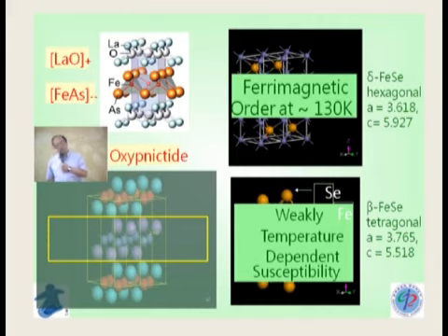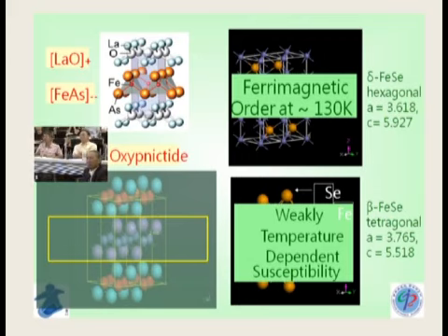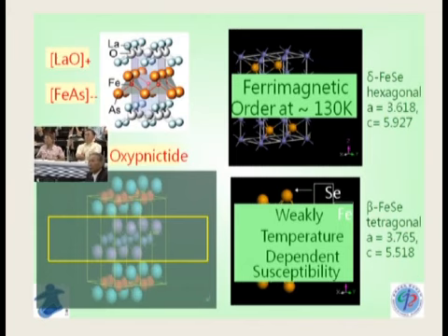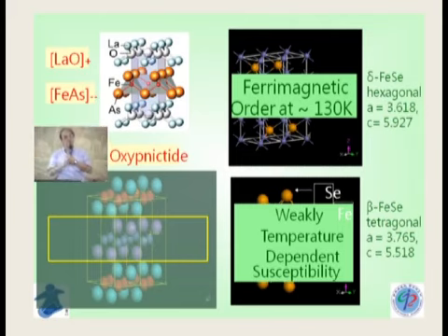To make the story short, indeed, we found in the literature that iron selenide already exists. It can be formed into a hexagonal structure, which is magnetic, with a magnetic order at about 130 Kelvin. However, if you manage to make it into a different structure, this tetragonal one, then magnetically it becomes very weak in its temperature dependence. So the magnetic feature somehow disappears.